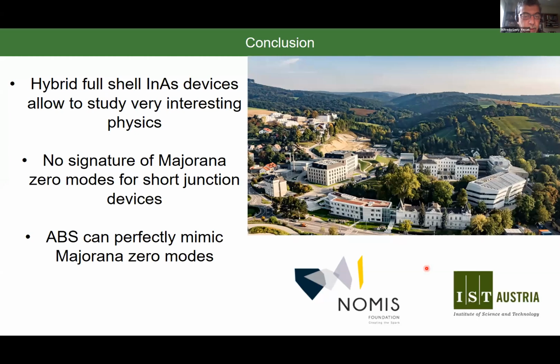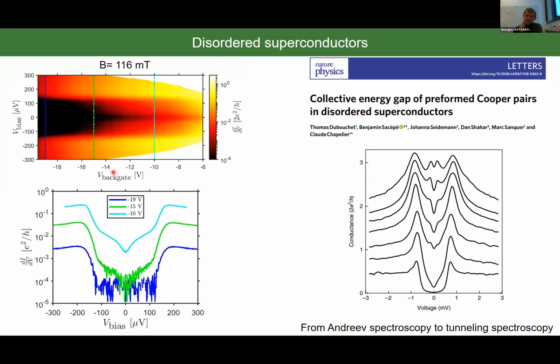And Juan Carlos Estrada: there is a zero bias conductance dip inside of a Zeeman split Kondo feature. It also shows in some of the finite field measurements when the superconducting gap becomes soft. Could you comment on the possible origin of that? Okay, I will speculate, so what I'm going to tell you is heavy speculation. For example, if you sit in the first lobe for one device and you measure differential conductance versus bias and backgate voltage, depending on where you sit with your backgate voltage, if you are really deep into the tunneling spectroscopy regime, you just see a hard gap. But if you tune your backgate, indeed you can see the evolution of this zero bias dip.